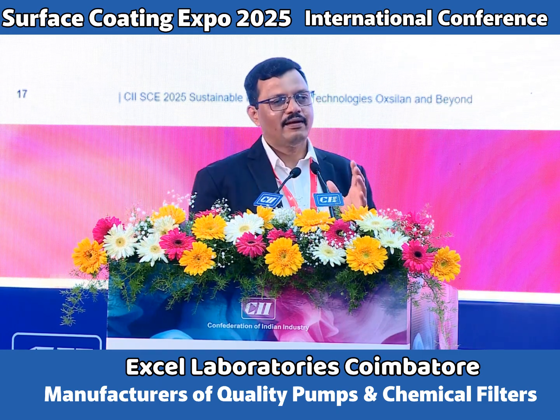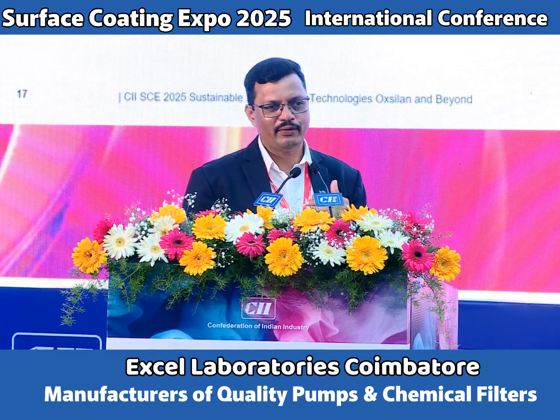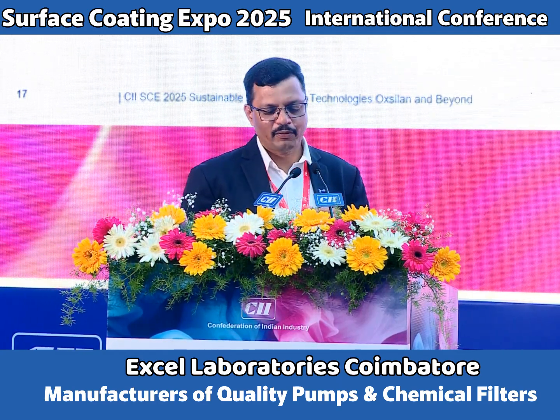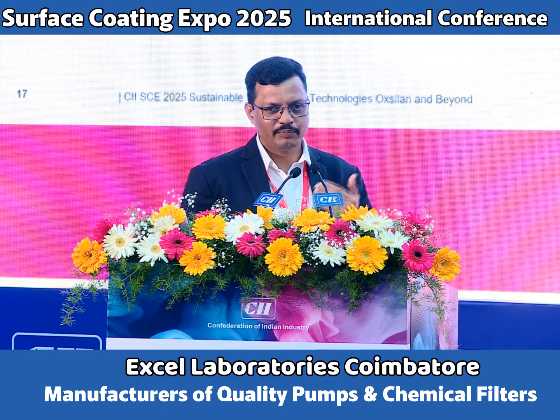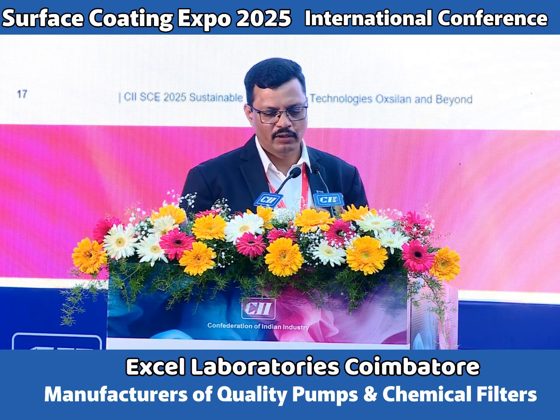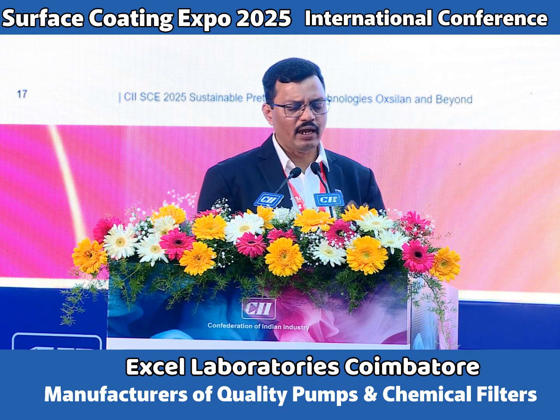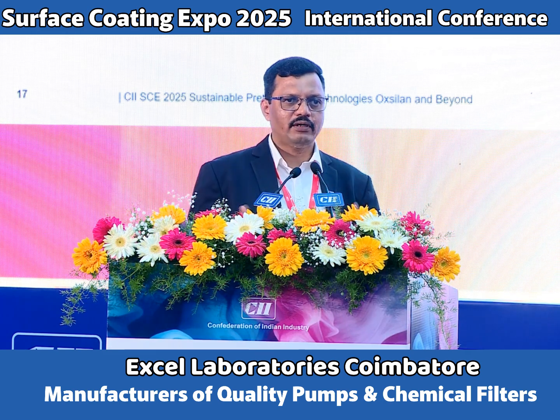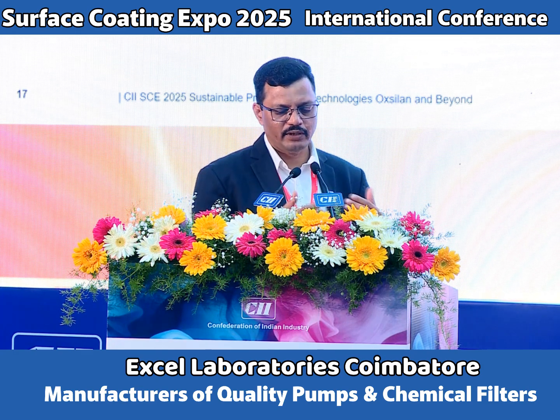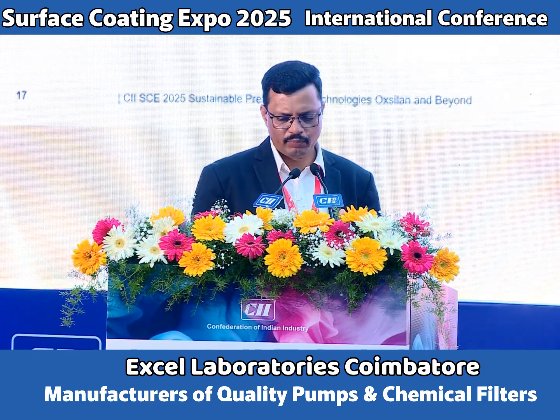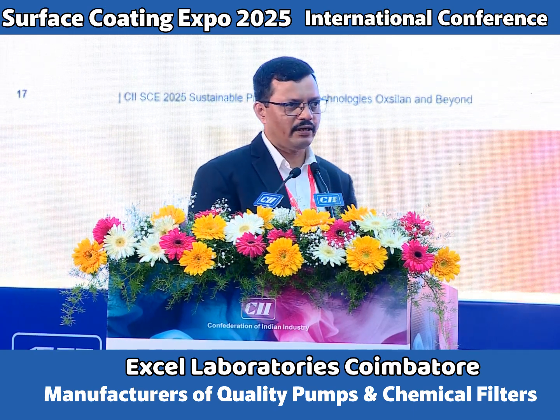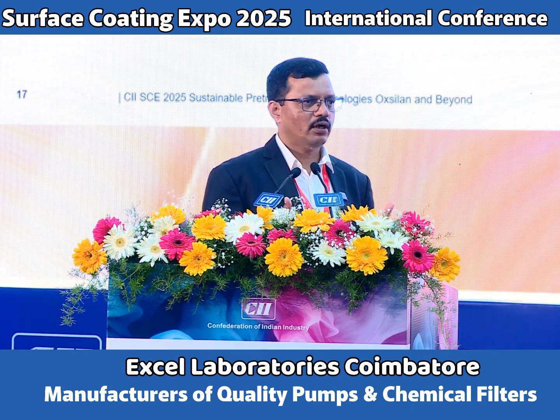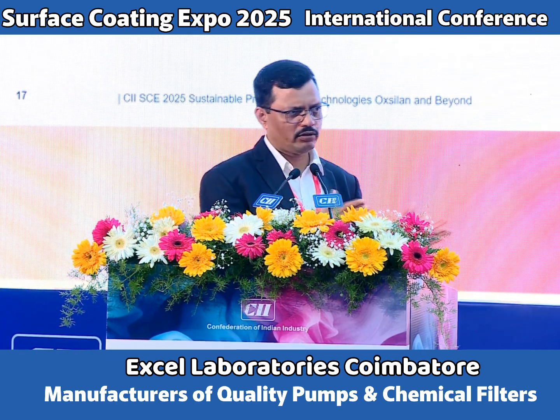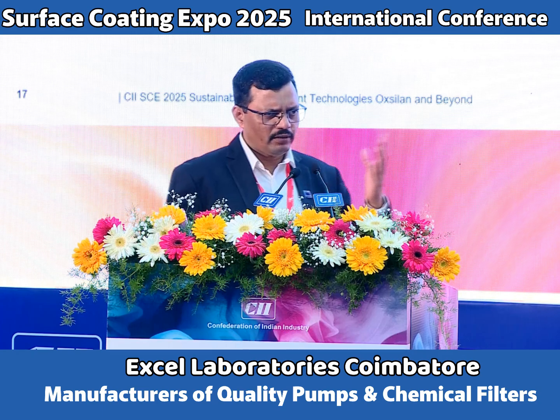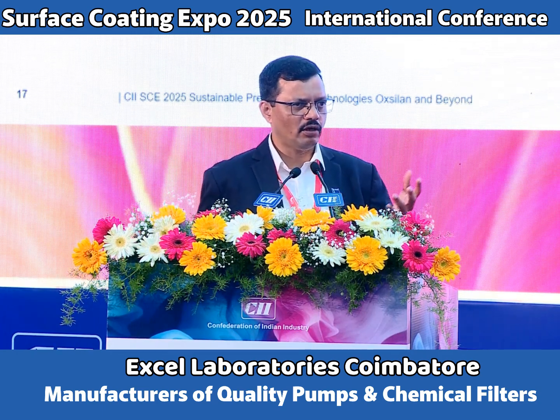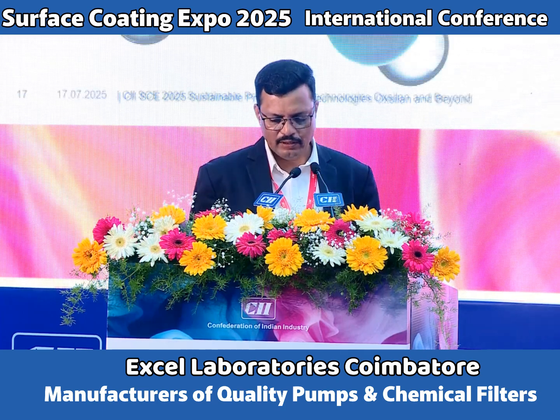Okay, this is the conventional zinc phosphate process, and the second row is the brownfield process, where we just have the drop-in replacement of the thin film technology in place of the zinc phosphate. Okay, and the bottom one is the greenfield project, where you want to set up a new facility. There we can have very leaner, very cleaner processes. So this particularly saves almost 10 to 20% of your capex, and it also reduces the utility consumption by almost 70%. If you want to understand more about this, definitely we have our stall at the Expo there. You can come and we will have more discussions.